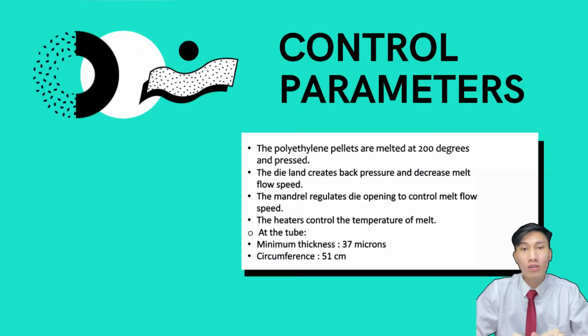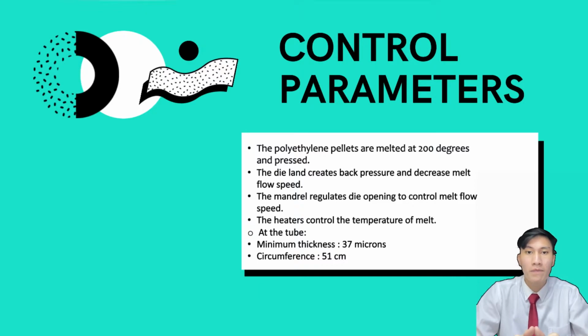So, these are the control parameters in the extrusion process. The first point is the polyethylene pellets are melted at 200 degrees and pressed. Then, the second point is the die land creates back pressure and decreases melt flow speed. The mandrel regulates die opening to control melt flow speed and the heaters control the temperature of the melt. And the tube has a minimum thickness of 37 microns and also a circumference of 51 centimeters.